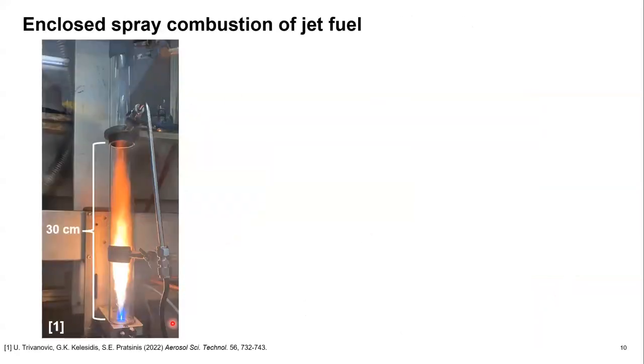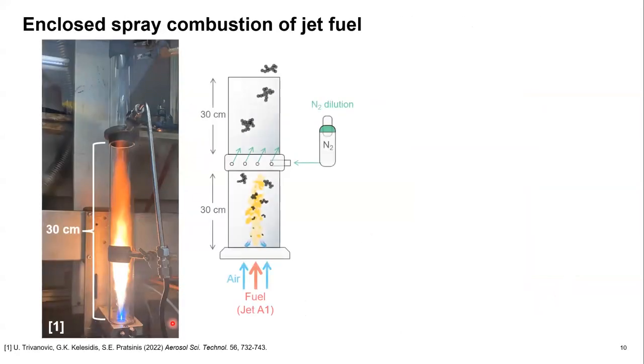Here we have a photo of our experimental setup, and I'll also show you some schematics. So what we did was we used about 4 milliliters per minute of jet fuel, Jet A1 in this case, that was supplied by a syringe pump. The fuel was surrounded by a high velocity oxygen flow, which disperses it into a fine spray. And surrounding that is a small premixed methane flame, which ignites the spray. Surrounding that is also sheath air.